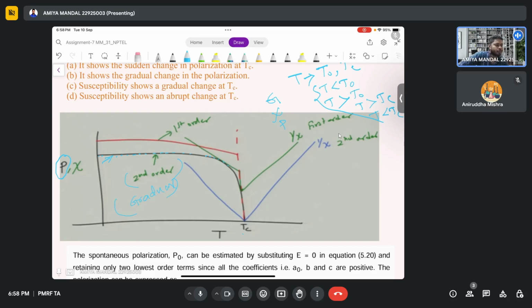And for first order cases, this red colored polarization value is decreasing abruptly. At this certain point, there is a bump. This is an abrupt change. Abrupt change of polarization gives this bump at a first order phase transition. Accordingly, the chi, the susceptibility, also changes at Tc according to the Curie-Weiss law, inversely proportional. So how does the 1 by chi value change? It is decreasing up to Tc and then increasing at the point of Tc. Tc is the transition temperature, the Curie temperature.